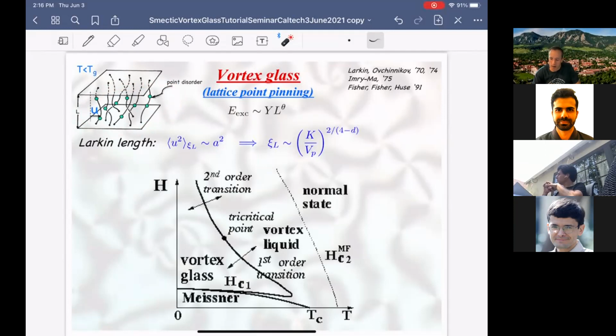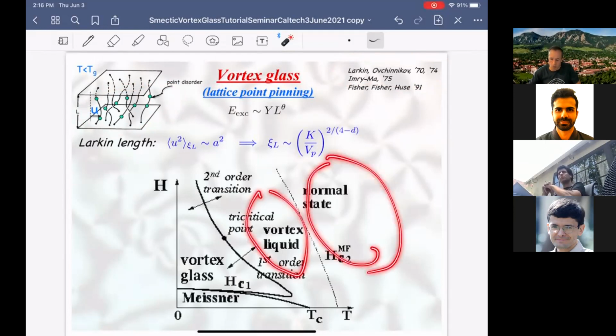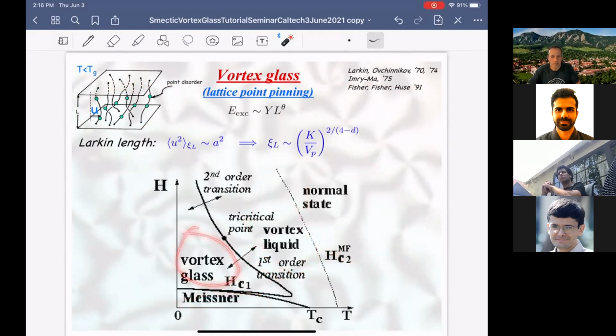This has a long history, actually predating high temperature superconductors. But it experienced a renaissance with high temperature superconductors. Now, in the previous phase diagram that I showed, in the absence of disorder, there's still a vortex liquid, there's still a normal regime, and there's still a Meissner state. But then the vortex crystal has been converted to what we call a vortex glass. At some point one could say there's a question mark here whether a vortex glass actually exists as a separate state of matter. But the upshot is that in 3 dimensions, we expect that it does exist in the presence of pinning disorder.